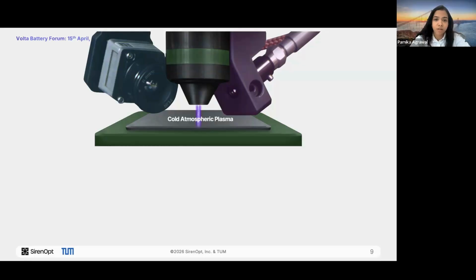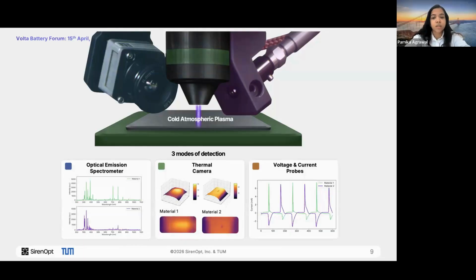So these plasmas, when they interact with material, that interaction is very rich. It has thermal signatures, optical signatures, as well as electrical signatures. And that is the essence of the metrology. So what we do is that we have three kinds of sensors. We have an optical emission spectrometer, we have a thermal camera, and we measure current going through the sample, which forms an electrical circuit with the plasma itself. And because of these three modes of detection, we get very rich raw data from our sensors.